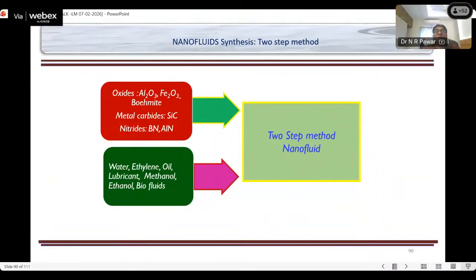Now, how to synthesize the nanofluid: in our research we have mostly synthesized the nanofluid using the two-step method. In the two-step method, we first synthesize the nanomaterials that we have discussed, whether boehmite nanoparticles, silicon carbide, alpha alumina, SiO2, and so on. These materials are then dispersed in a base fluid like water or ethylene glycol. Then the mixtures are stirred by a magnetic stirrer or by centrifugation, and can be converted into the nanofluid.